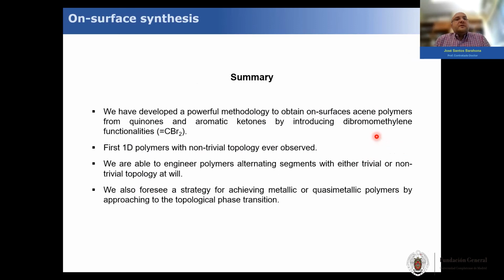Well, and finally, as a summary, I have to say that we have developed a very powerful methodology to obtain polymers of acenes and periacenes, starting from very cheap precursors on top of the surface. These polymers, I'm quite sure, are the first one-dimensional polymers that show a non-trivial topology. We have also demonstrated that we are able to engineer polymers that have alternating segments of either trivial and non-trivial topology, which is something interesting, which might at some point have a certain application. And most importantly, we have foreseen a strategy for achieving metallic or quasi-metallic polymers by approaching the topological phase transition, as is the case of the Pentacene molecule.